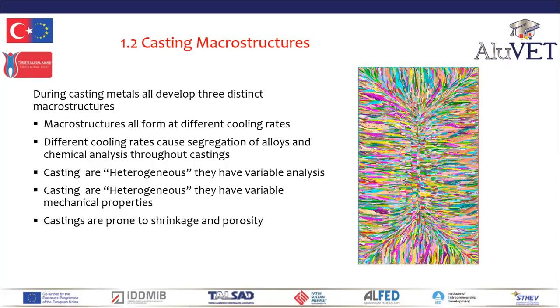So let's now give an overview of casting macrostructures. So during casting, all metals will develop 3 different macrostructures. The macrostructures will all form at different cooling rates. The different cooling rates cause segregation of alloys and chemical analysis during the castings. So castings are heterogeneous. They have variable analysis. Castings are heterogeneous, so they have variable mechanical properties. And castings are prone to shrinkage and porosity.